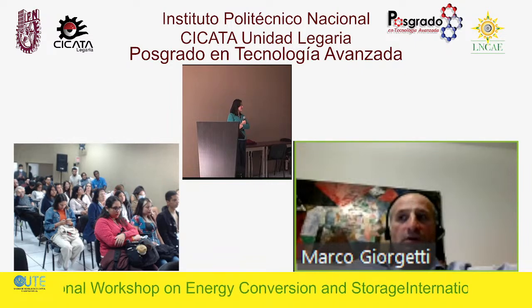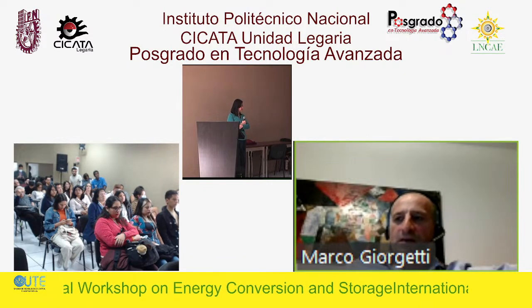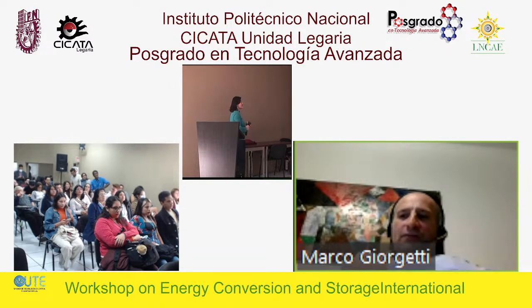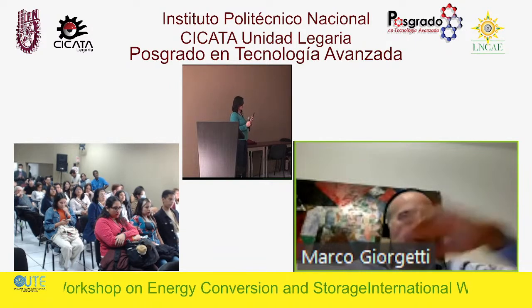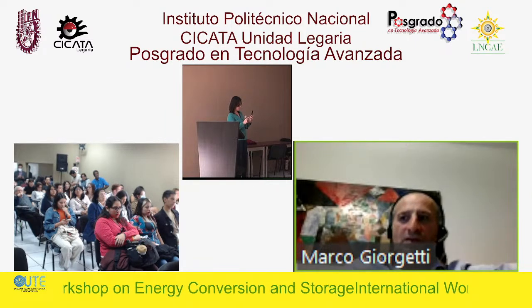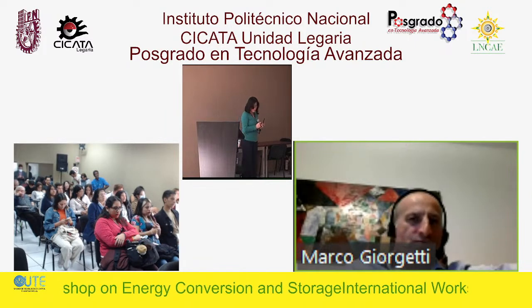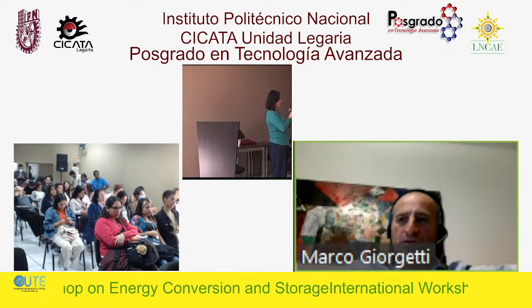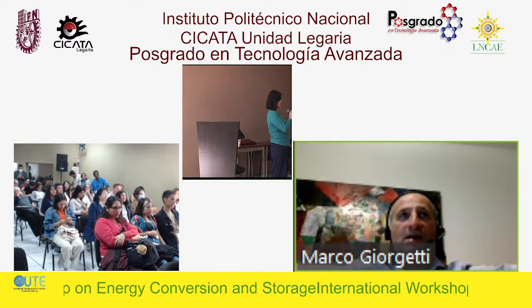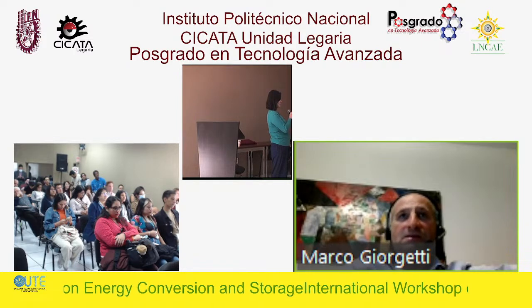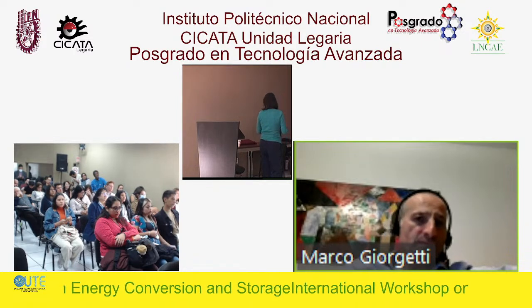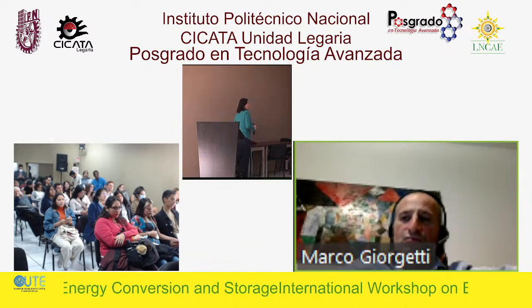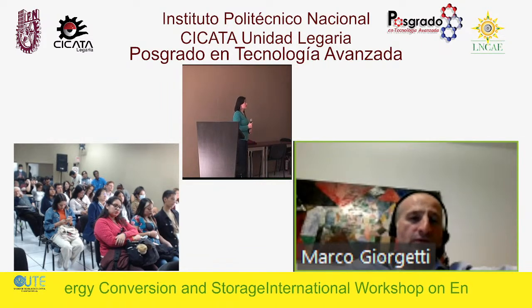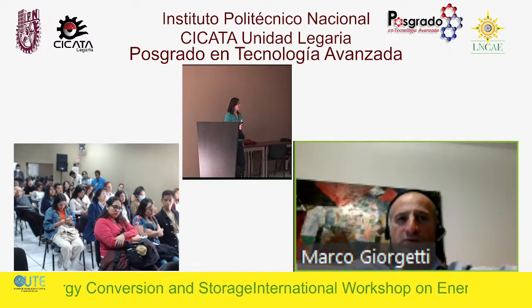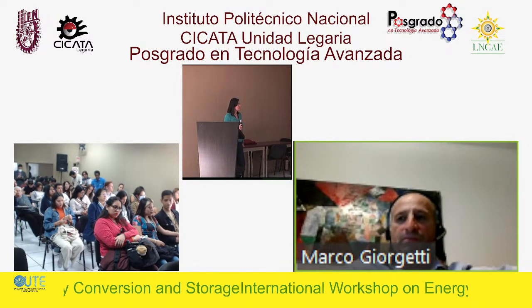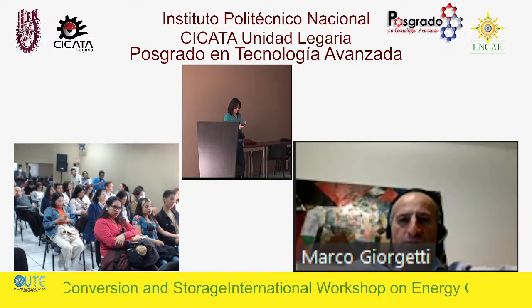But especially on sodium, because lithium, as you know, it's very difficult to check the position of the lithium. Anyway, even if you go to the synchrotron, you have this measurement with high resolution, this is something that you can do. But what I can say is that sometimes it will be possible, especially on sodium. So you can try to finalize also the atomic position for sodium. It could be possible, but just the sodium. Okay, thanks very much. Sure.